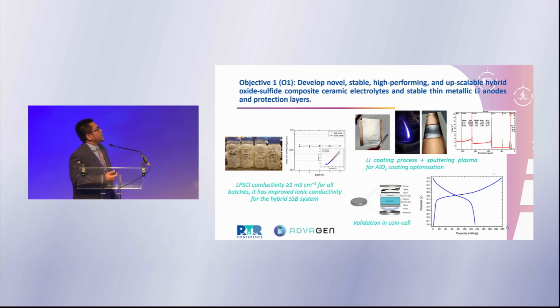And next, for the lithium coating process, we first try sputtering with ALOX coating optimization, so that we can get several nanometers of aluminum oxide, which is already proven by XPS as well. And we can validate it in a coin cell at room temperature. We get around 130 milliampere hour per gram.